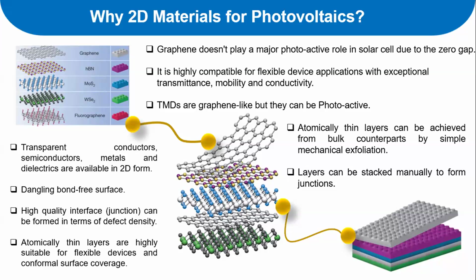Some other materials called transition metal dichalcogenides mimic the graphene hexagonal honeycomb structure, but they have an optical band gap, as we presented in the previous slide. These are 2D layered semiconductor materials like molybdenum disulfide or molybdenum diselenide, tungsten disulfide or tungsten diselenide. They have an optical band gap. The values are 1.3 electron volt, 1.8 electron volt, 1.5 electron volts. They are different, and they depend on the thickness of the material, the number of layers that have been stacked in that material. So we can use them as a semiconductor, unlike graphene. And they mimic the graphene mechanical properties and electrical properties, just like the hexagonal honeycomb structure. So they are very attractive. They are atomically thin, so we can use them in flexible devices as well.